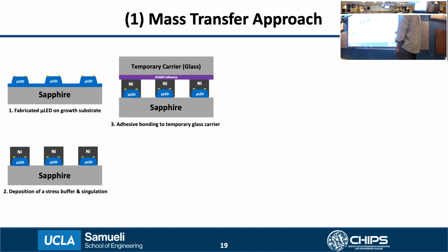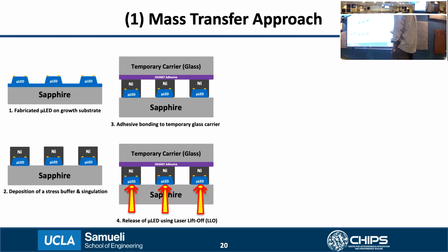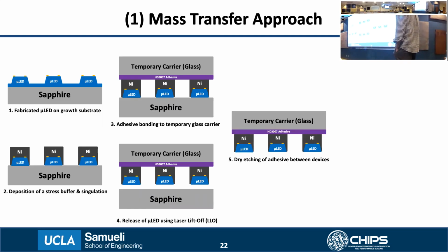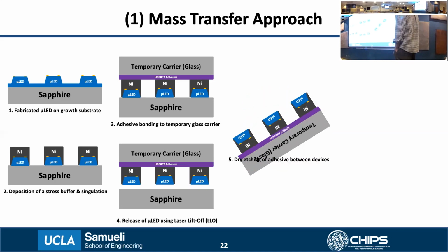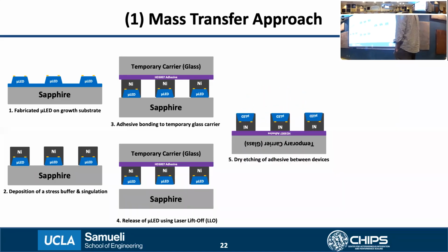Next, in step 3, you can see that these singulated devices on the sapphire are bonded to a temporary glass carrier with the HD9007 adhesive, which is a thermoplastic polyimide which we use for this adhesive bonding process. And then we perform a laser liftoff step, which detaches these LEDs from the sapphire substrate and completely transfers them onto the temporary glass carrier. Next, in step 5, we do some basic cleaning on the surface and also dry etch the adhesive between the devices so that the adhesive is also now patterned.